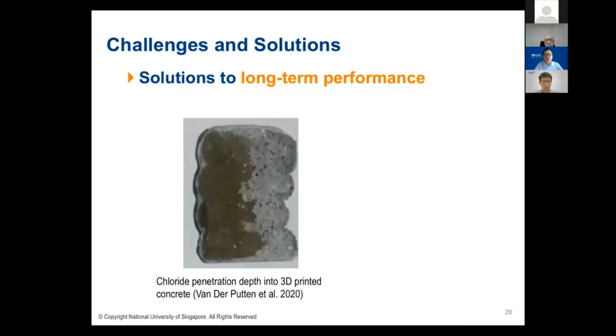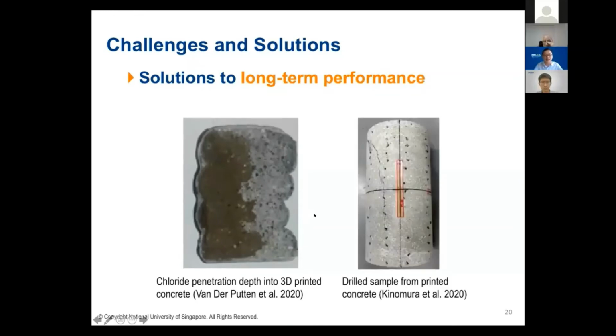Okay, the last challenge to 3D concrete printing in the talk today is the long-term performance. The research in this area is very limited because people just started working on 3D concrete printing. But earlier this year, one research group in Belgium started to look into how is the performance of the concrete in the chloride environment. So you can see the white color or the silver color is the chloride penetration depth. One thing to note is that this is the interlayer, so actually the penetration depth would be deeper at the interlayer place. I think this is strongly linked with the pore structure.